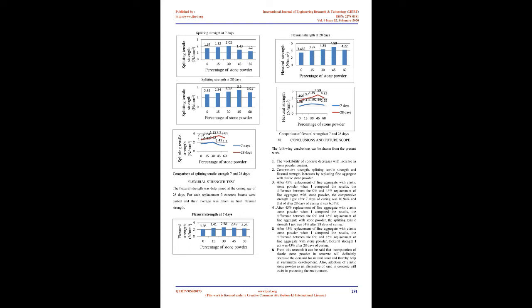Flexural strength test, IS 516-1959. For determination of flexural strength, concrete beams having size 700 mm x 150 mm x 150 mm were cast, demolded after 24 hours and cured for 7 and 28 days.